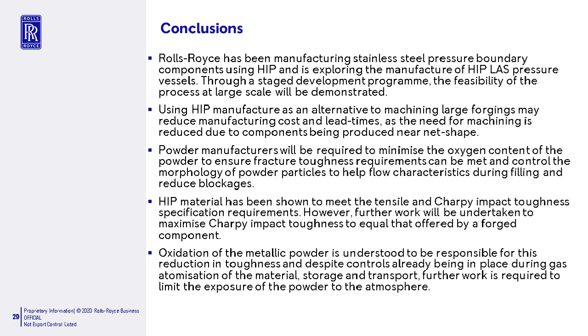And to date, we've shown that the HIP material can meet requirements, but via further refinement, we think we can improve Charpy impact toughness to the forge level. And just to make it abundantly clear, oxidation of powder needs to be fully understood and controlled if you're going to achieve toughness and the required material properties that you need for nuclear components. Very exciting project, quite a move away from traditional processes to give us some real advantages for nuclear pressure vessel manufacturing and also the wider nuclear component manufacturing by moving to the additive HIP process and EB autogenous non-filler welding processes.